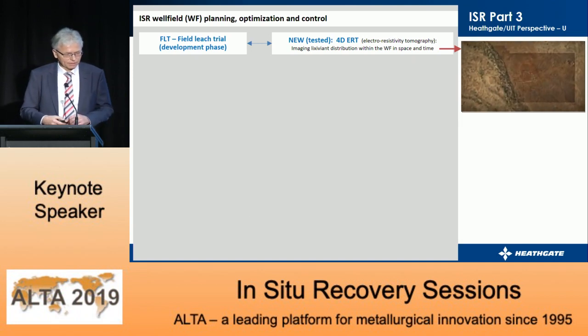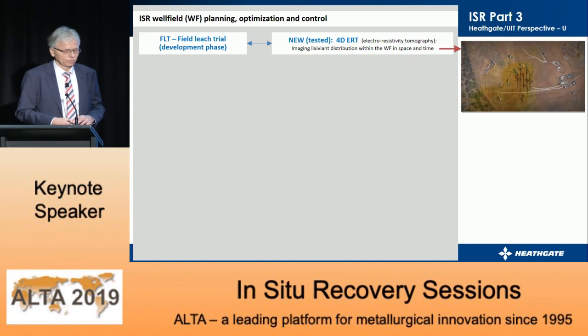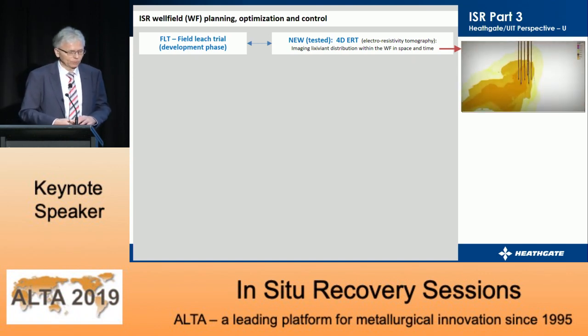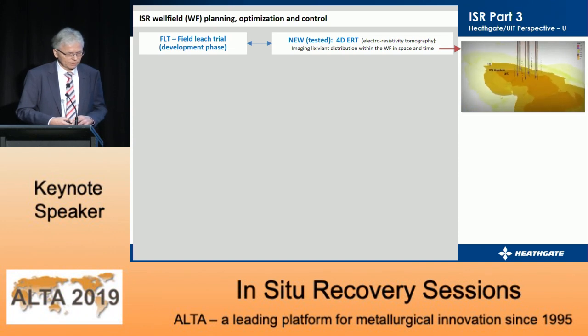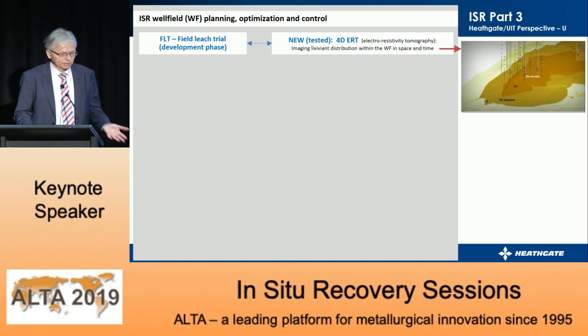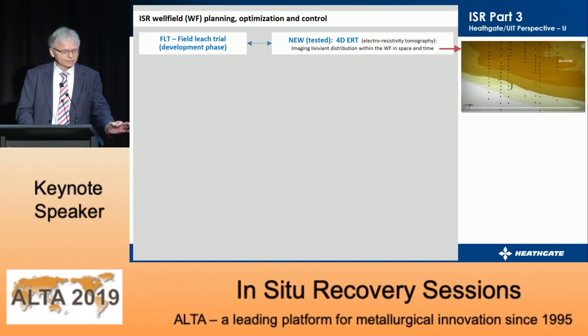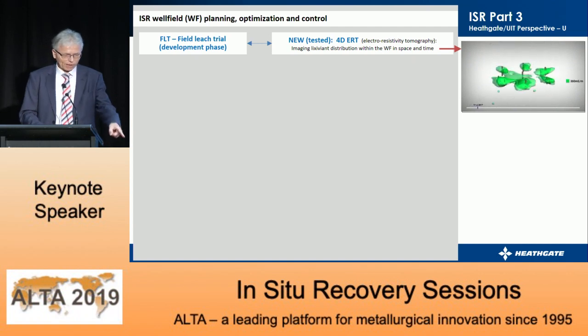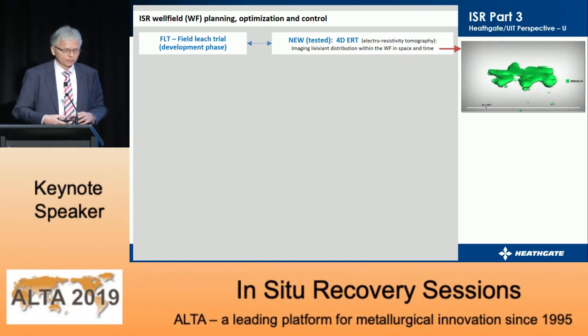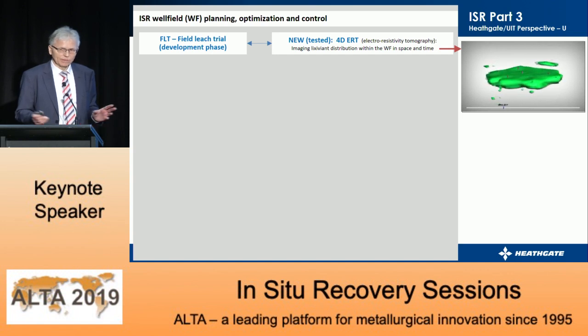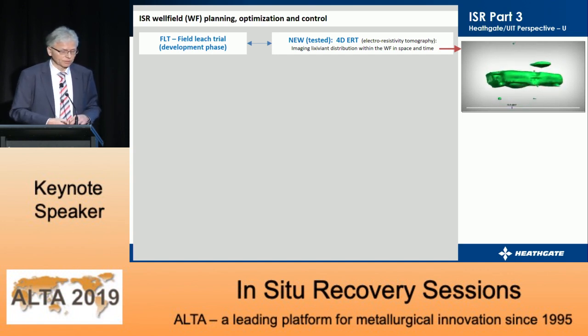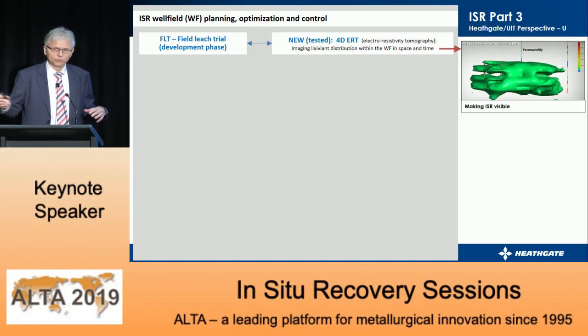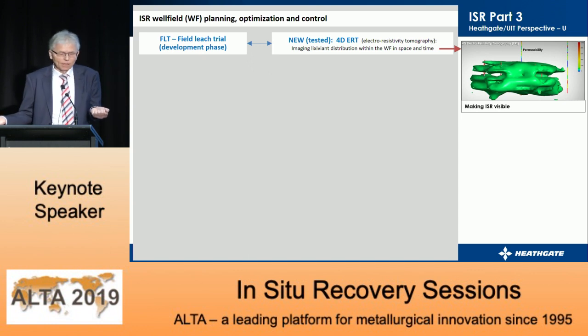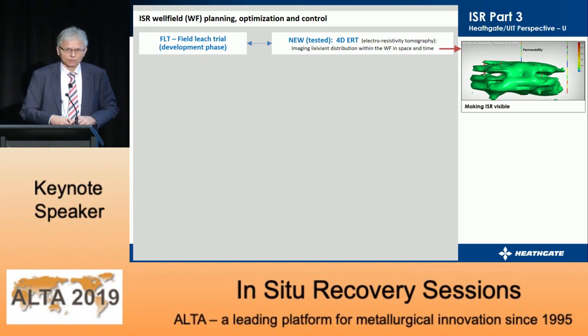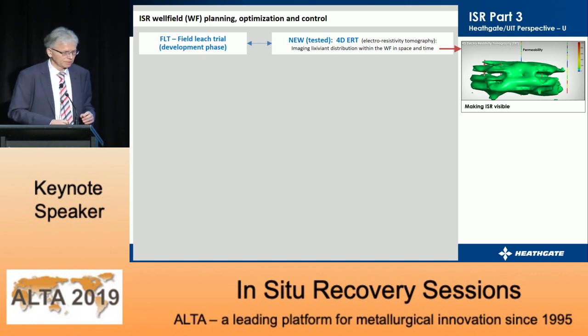There is a field leach trial wellfield pattern, a 7-spot one with 6 injectors surrounding 1 extractor. There is the ore body outline, and then we start to operate this particular wellfield pattern, and you can visualize the fluid flow in the underground right from the start-up due to the imaging and the electroresistivity, due to the highly conductive lixiviant flow. That was very conclusive for our hydrologist in particular, and we have seen that the fluid flow is not homogeneous in general, and there are some heterogeneities well explained by the permeability profile in the underground.